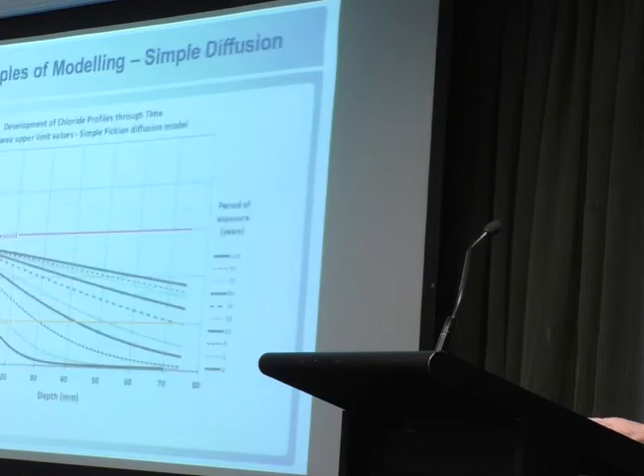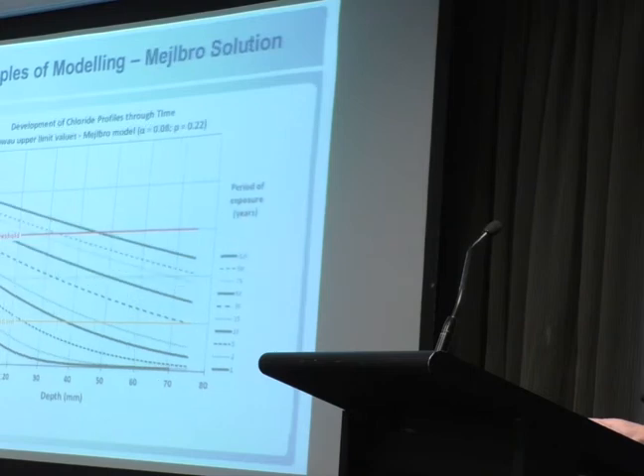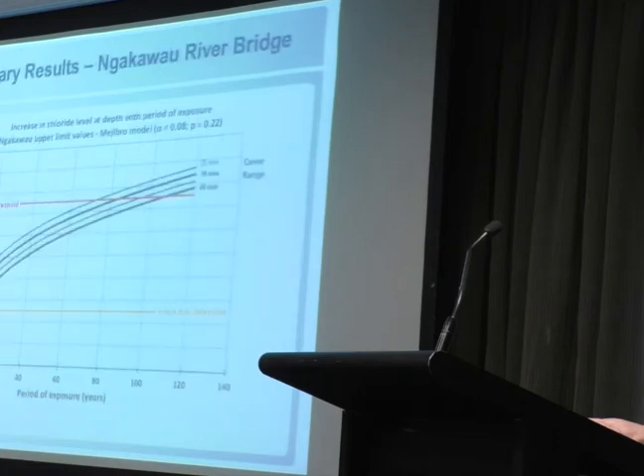So just looking at the profiles, this is the modeled evolution of the chloride profiles with time based on a standard Fick's law solution. You'll note that the surface chloride concentration stays constant with time. If you use the Mejlbro solution on the same data, you see it does make a significant difference in the result and the level of chloride contamination you're predicting at the reinforcement with time. That just shows the same data presented in a different way, so increase in concentration with exposure time.